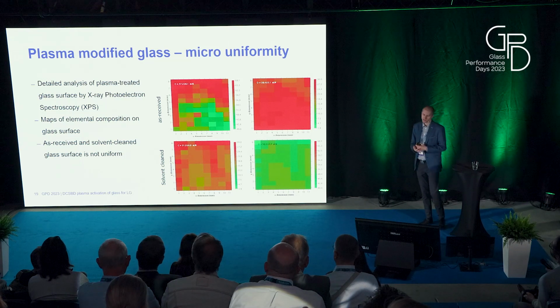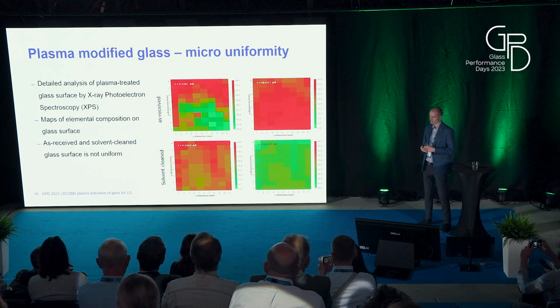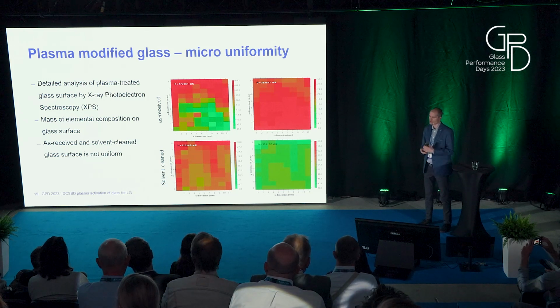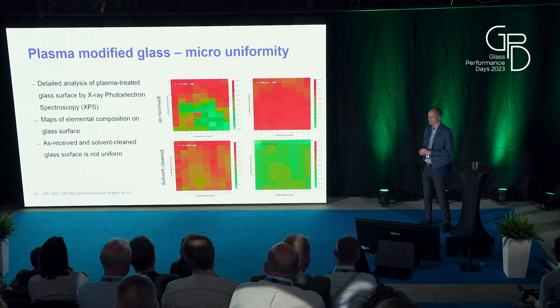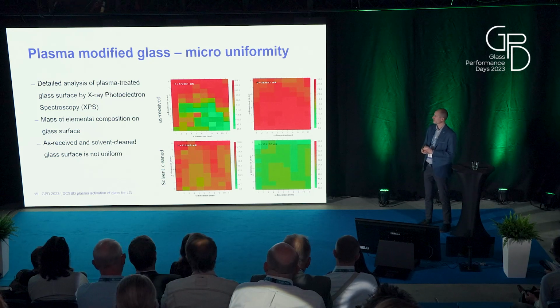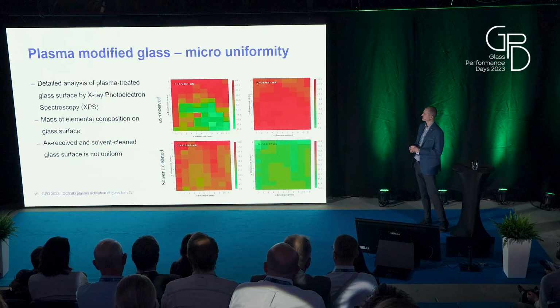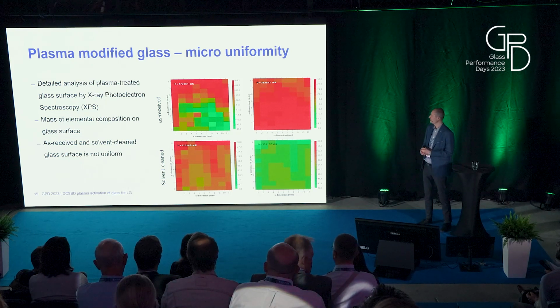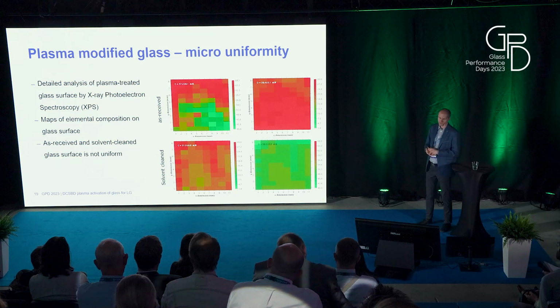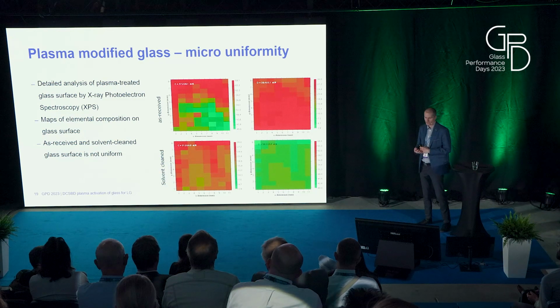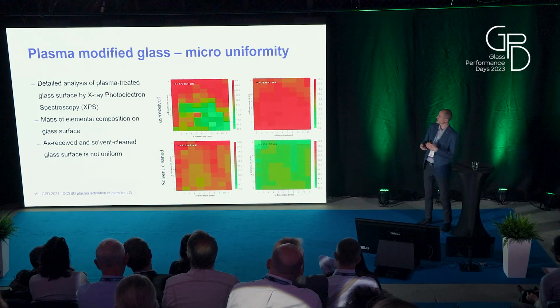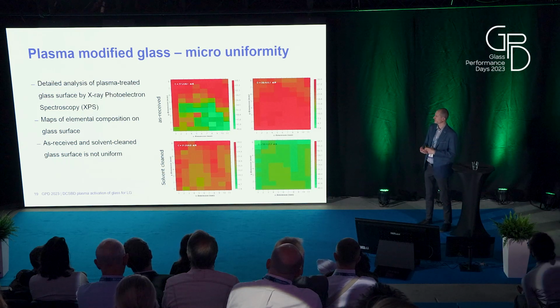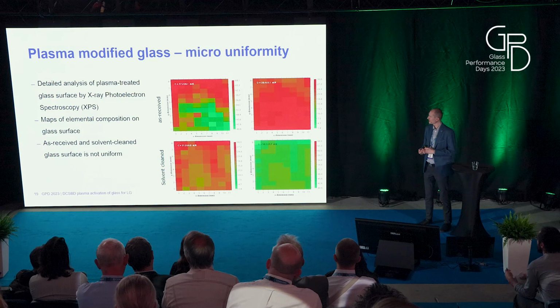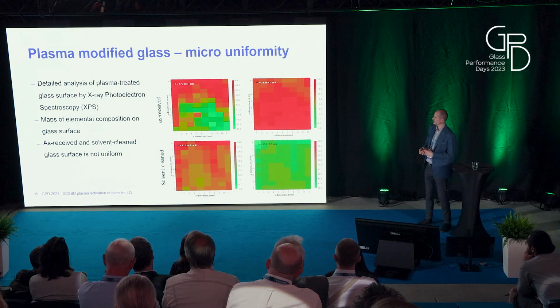In our work, we also analyze the micro-uniformity of the glass, because this micro-uniformity is especially important for the delamination effect, for example. Therefore, we created concentration maps of the elements, especially carbon, oxygen, and silicon. You can see in this top left graph that there is a huge variation of the carbon element on the surface of the as-received sample. There is a change from this red color up to the green one.